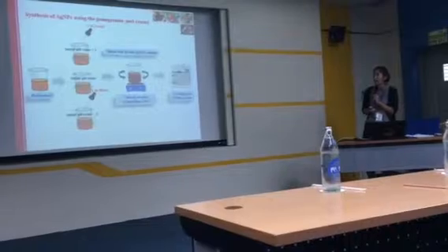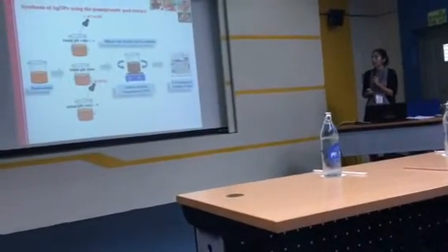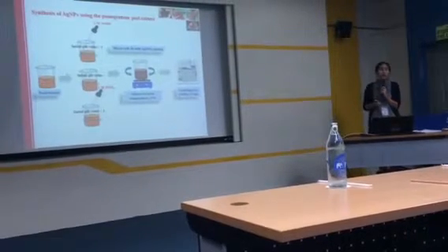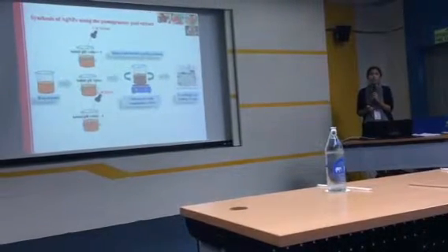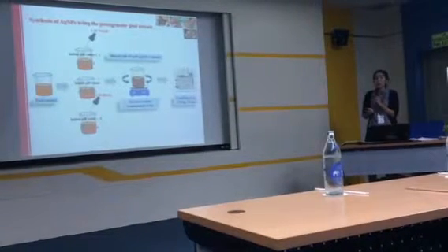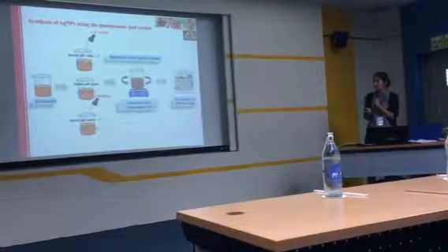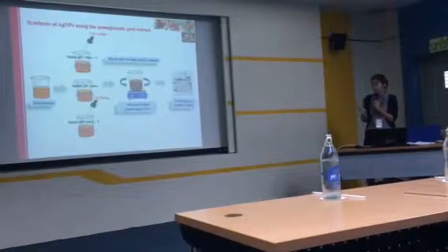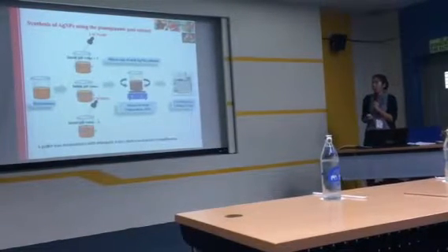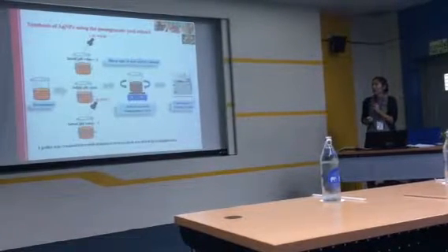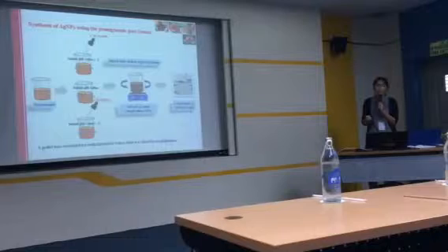The peel extract was mixed with 10 millimolar silver nitrate solution. The solution was stirred at room temperature for 24 hours. The silver nanoparticles were collected using centrifugation at 12,000 g for 15 minutes. The pellet was washed with deionized water, then dried by lyophilization.